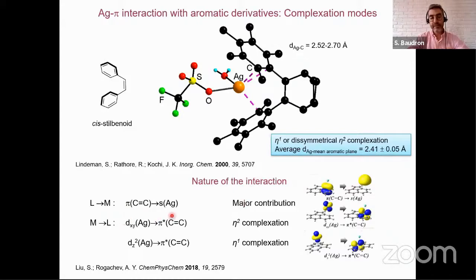But this secondary contribution that determines the way this silver cation sits on top of a carbon-carbon double bond depends on the nature of the carbon atom or the coordination site that is involved. When we have a dxy orbital that is more involved, you have a tendency to eta2 complexation, while with a dz2, you have more of an eta1, and this is usually what determines whether you have one or the other. But the examples I'm showing here are mostly polyaromatic systems.